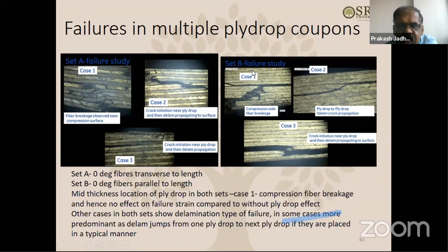For set B here, you can see case one is compression side fiber breakage. Case two is ply drop to ply drop delam crack propagation, as you can see. And the third case is crack initiation near the ply drop and then delamination propagating to the surface. So basically, crack is initiating somewhere and then propagating to the surface. Okay. Set A, set B, of course, I explained that set A is 0 degree fibers transverse to the length, and set B is the 0 degree fibers parallel to length. So mid thickness location of ply drops in both cases, case one compression fiber breakage. Okay. Hence, no effect on the allowable strain. Other cases show it much more predominantly as the delam jumps from one ply drop to the other.